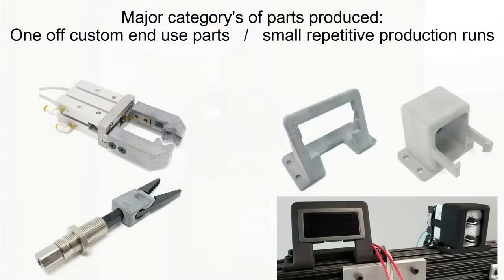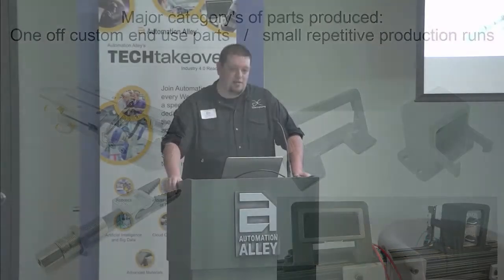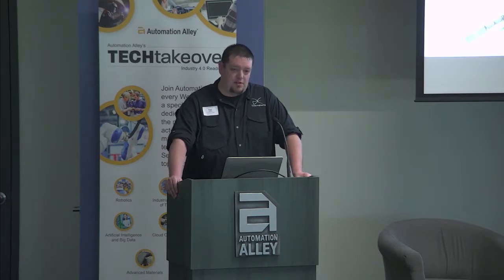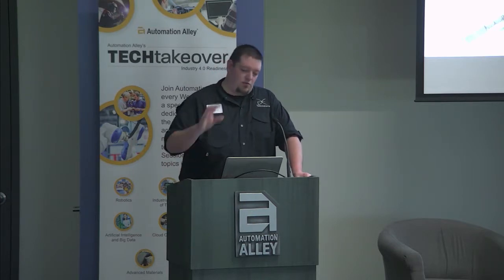The material's good up to, on the box, it says good up to about 360 degrees Fahrenheit. And it's stable up to those temperatures. We've experimented with going over that momentarily. So what we'll do sometimes is grab really hot parts out of injection molds, maybe 400 plus degrees. We'll reach in, grab the part, quickly drop it someplace else, and hit the MJF part with an air blast to help dump heat out of it.